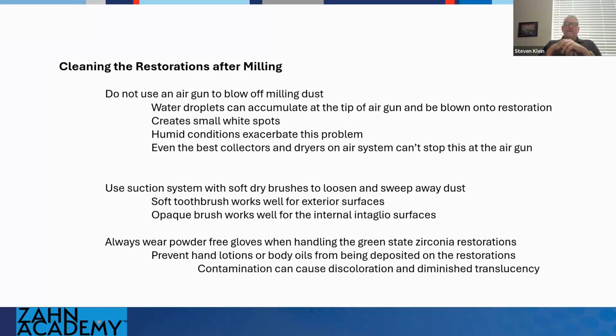The other thing too, I would say is powder-free gloves. Make sure they're powder-free, because that powder can have a reaction with it as well. You can get that deposited into the surface, especially that first one or two crowns that you use when you put the brand new gloves on. You could be depositing that powder directly into that surface of the zirconia, and it's important to avoid that.